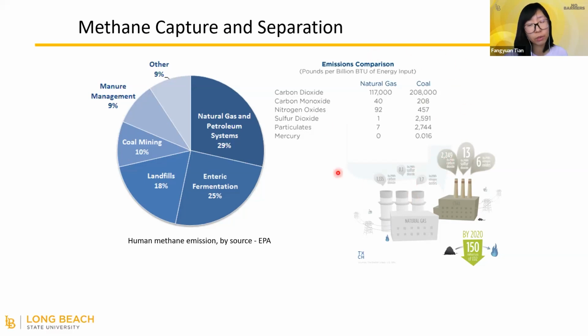and natural gas we can use as energy. And if you look at this table, we found that methane delivers roughly twice the energy compared to coal in terms of the amount of carbon dioxide released. And based on the EPA data, we noticed that the natural gas and petroleum systems together with the landfills take up almost 50% of the human-related methane emission every year. And we can use that methane released to the atmosphere as energy. Especially since methane is a greenhouse gas, and we're trying to minimize its emission.